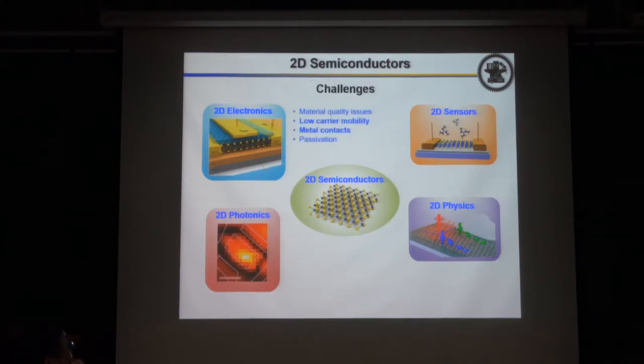But we still have many challenges, like the material quality issues. Now we're still trying to grow single crystal, large area, up to wafer scale. And also low carrier mobility, metal contact, and passivation. And in 2D photonics, the low quantum yield is still a big issue in this field, and also the very short photocarrier lifetime. And also we still don't quite understand the process of exciton formation and the exciton dissociation process in the material. So we still need some new experiments to understand the underlying mechanism and process.